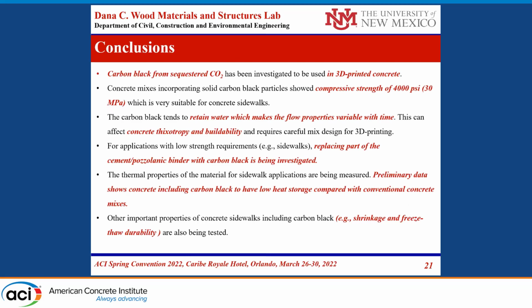So to summarize and conclude what we've presented, carbon black sequestered from CO2 has been investigated for use in 3D printed concrete. Concrete mixes incorporating this solid carbon black showed compressive strength in the 4,000 PSI or 30 megapascal range, which is very suitable for concrete sidewalks. I still think it's too high, so we actually can go lower. I think something in the 15 MPa, 2,000 PSI range is enough for sidewalks.